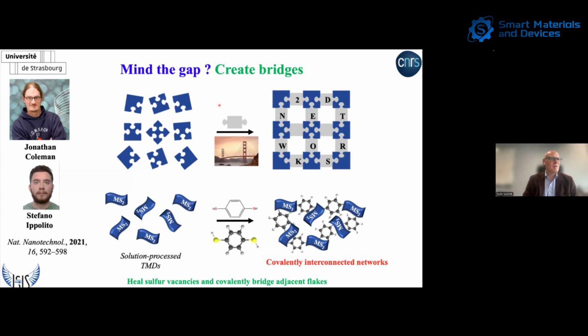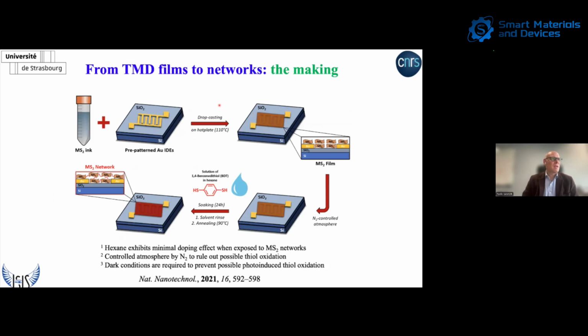Now, how do we prepare this kind of network? That's pretty simple. We get the ink in ethanol coming from Jonathan, and then we buy some interdigitated electrodes supported on silicon dioxide, and then we drop cast our ink. We create this kind of film, and I use the word film when the flakes are disconnected. Then we put this in a nitrogen controlled atmosphere, and then we apply a drop of our benzene dithiol. Now, this has to be done in the dark and inside the glove box, which allows us to avoid photo-oxidation.